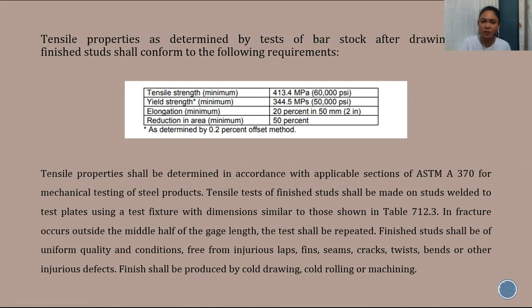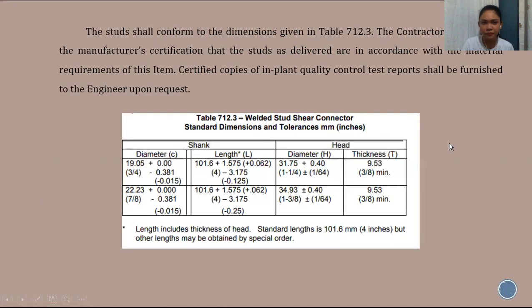The tensile properties shall be determined in accordance with the applicable section of ASTM A370 for mechanical testing of steel products. If fracture occurs outside the middle half of the gauge length, the test shall be repeated. Finished studs shall be of uniform quality and condition, free from injurious laps, fins, seams, cracks, twists, bends, or other defects, and the finish shall be produced by cold drawing, cold rolling, or machining. So, under sa tensile test, if nag-fracture siya outside the middle half, usabon nimo siya og test. The stud shall conform to the dimensions given in the table below.